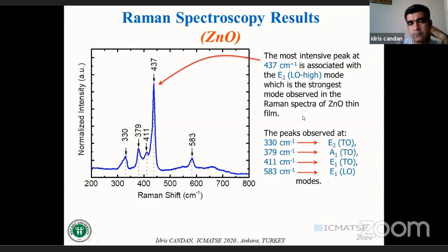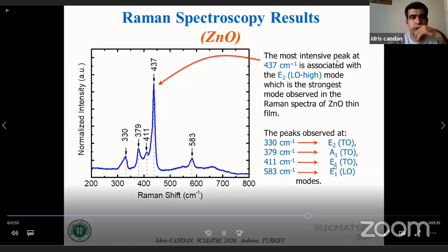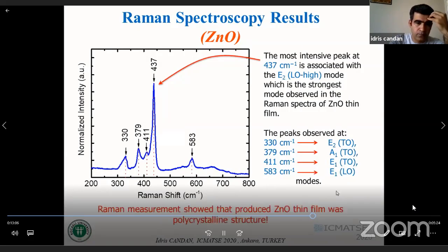And the other peaks observed at 330 are related to E2 TO and 379 A1 TO and 411 related to E1 TO and 583 related to E1 LO modes. Raman measurements show that the produced zinc oxide thin film has a polycrystalline structure.